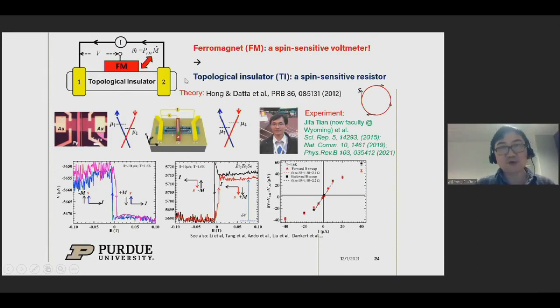One of the important applications of these spin helical electrons is that if you pass a current, that current is automatically spin polarized. And you can measure this with a spin-sensitive voltmeter. And the ferromagnet is basically a spin-sensitive voltmeter. Depending on the magnetization of this ferromagnet, you can measure different values of voltage or resistance, which switches when you switch the magnetization using a magnetic field. But the direction of the switch also reverses when you change the direction of the current. So this directly demonstrates spin-momentum locking. So in this sense, a topological insulator is a spin-sensitive resistor, you may say.